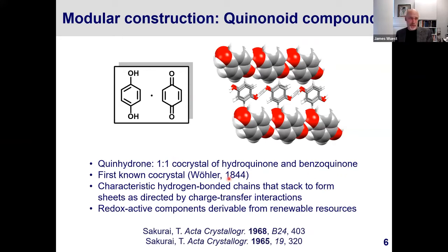It's historically important because it was the first example of a co-crystal, and it was reported by Friedrich Wöhler in 1844, so it's been known for a long time. The structure is very characteristic and in a sense very logical. So you see here hydroquinone. It forms a hydrogen bonded chain with benzoquinone that alternates. So now we have a new hydroquinone. And the chains stack in a way that's directed by charge transfer. So behind the benzoquinone here is a hydroquinone. And so this defines sheets, and the structure is built up of these stacked sheets.